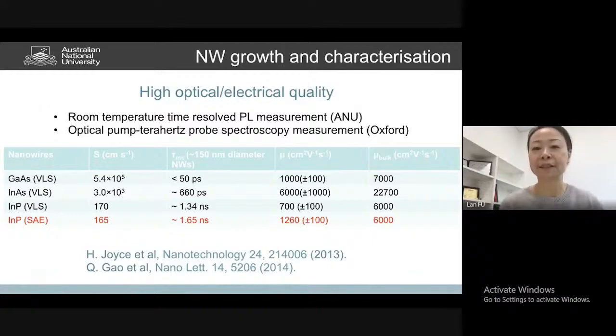For semiconductors, the higher the mobility, the better: the faster the carrier transport under the electric field, the better the transport performance. So all this we've done, and we find that our indium phosphide nanowires grown by selective area epitaxy, compared to other growth, have very low surface recombination velocity, very high mobility, and a very long carrier lifetime. All this indicates a good material quality, which you can use for device applications.